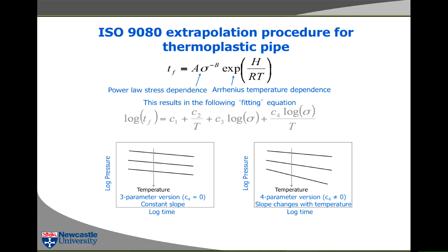And what Arrhenius said, everything is in motion. You know all atoms are in motion, they're undergoing thermal motion. And the more you heat up the material, the greater the motion. So if there's an energy barrier to overcome, quite often the energy state here will jump up and down, just as a result of atoms colliding with each other. And once in a while, this energy will be high enough for the thing to fall over the wall. And it's called an activated rate process.